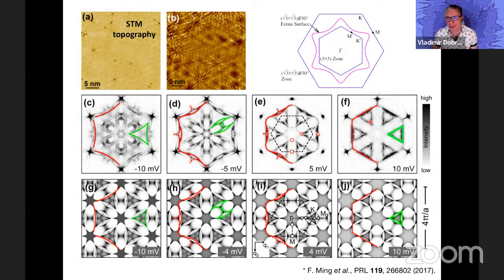Maybe there are things that are missing, but it just seems to me like, for example, in Mott organics, which are also triangular one-band models, and they've seen some superconductivity, you can directly measure the Fermi liquid coherence temperature and the quasiparticle weight using different ways, including optics. And there are substantial renormalizations in those materials. These are real materials. I'm not talking about theory. So I wonder, how can it be that this is weakly correlated in this regime? Well, it's certainly looking like it's weakly correlated near the Fermi level. I don't know what's happening with the overall bandwidth. So I don't know how momentum and energy dependent this is. I agree with you, it's surprising.